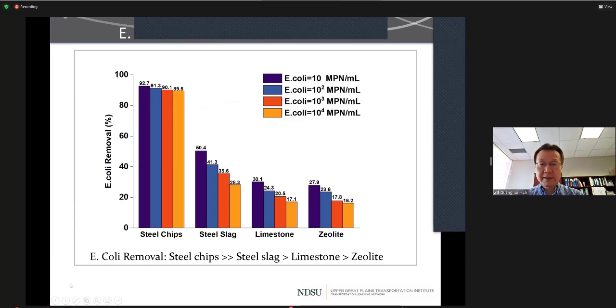And also we evaluated the impact of different influent E. coli concentrations on the adsorption efficiency of the four materials. For steel chips, over a wide range of influent concentrations, the removal efficiency did not vary by that much. It varied from 89.5 to 92.7 percent. So we were able to achieve very good removal efficiency over a wide range of influent concentrations.